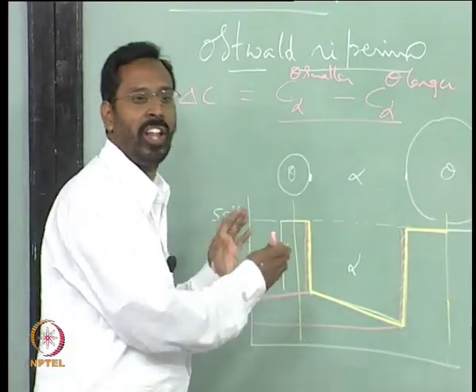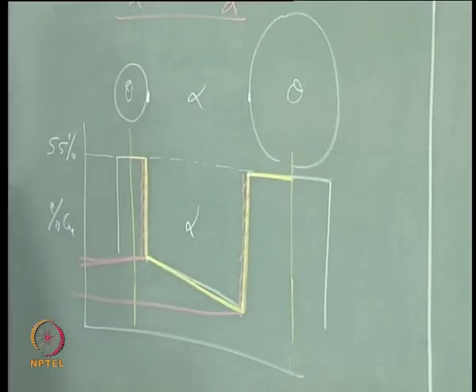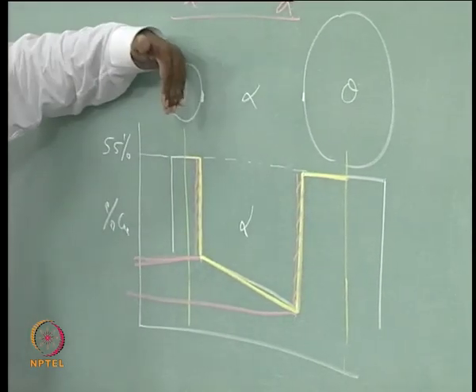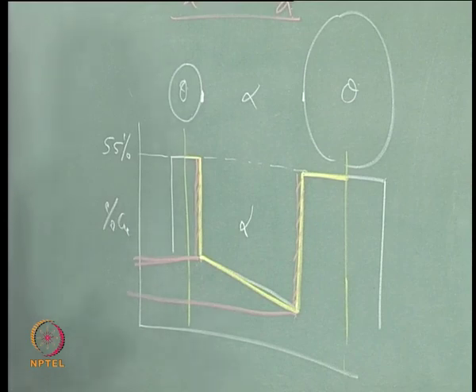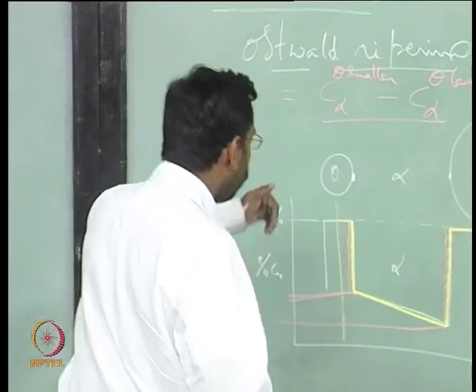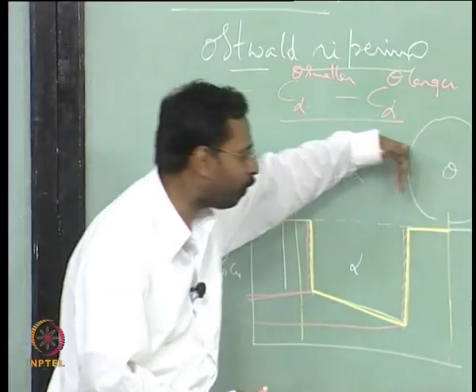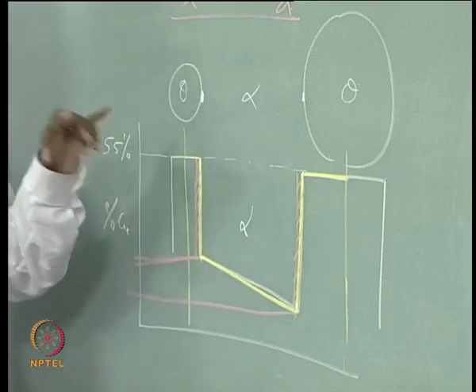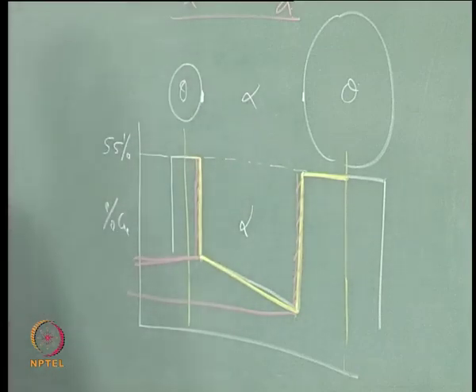And of course, you may ask what is going to happen to the dx in dc by dx, when this theta is growing and this is decreasing. In principle they may remain the same or change to some extent, but we do not know the rate at which this decreases and the rate at which this increases. So, there may be a small change in the dx also, but in dc you can see a significantly large change, because of which, as time proceeds at that temperature, you will see the flux, the rate at which the atoms move, is going to be higher and higher.